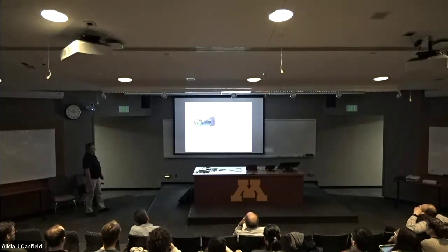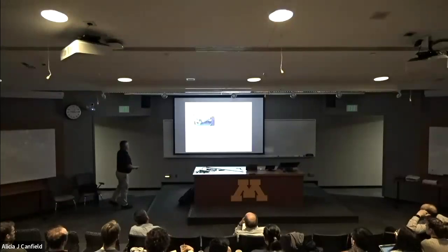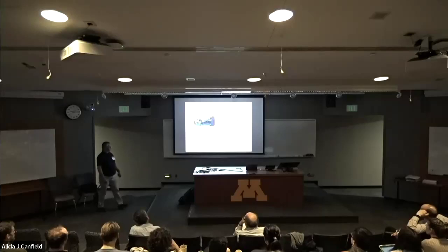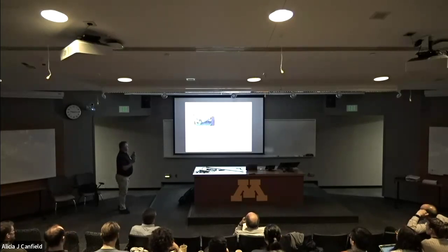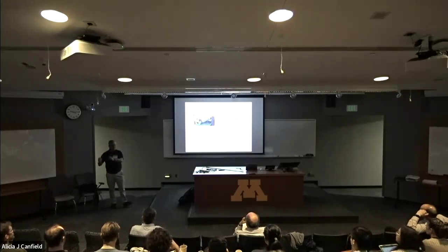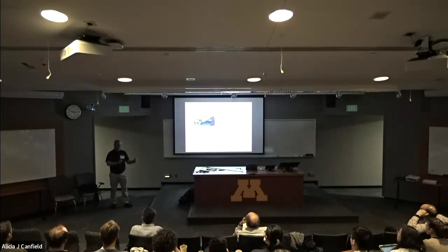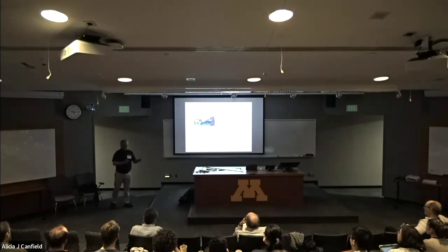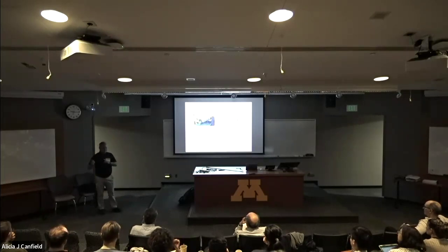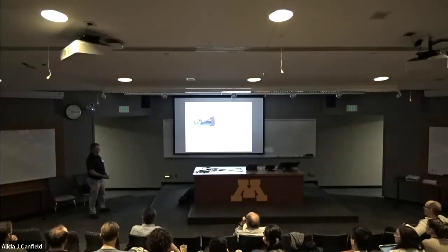So our approach to investigating why this is was to do an experiment which is really kind of horrible conceptually. You take your beautiful material and you junk it up to see what's going to happen. And the reason that you're doing that is that you always wonder in the modern world, when you have a very high conductivity, do you have a very good material, or do you have some scattering matrix elements that are preventing backscattering and allowing you to work with a crap material and get a great result? Here we're going to see that, and this is something that Chris's group and the posters outside will emphasize, it's a very interesting combination of the two things, at least.